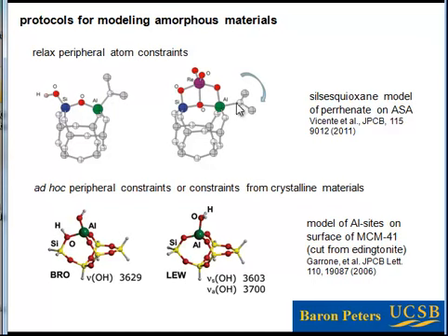And then this 4-coordinated aluminum interacts with this perrhenate species, and when it does that, you see that what happens is the perrhenate, a strong Lewis base, pushes aside the siloxane group that was placed here. Now that's fine. I mean, this is sort of the way the calculation was set up. The problem with this kind of approach is that it's probably unrealistically flexible, right? So this siloxane group, these silicons have moved by something like 3 angstroms.